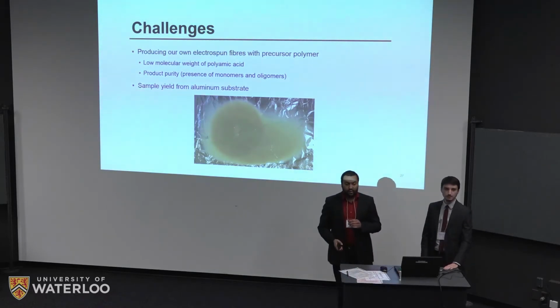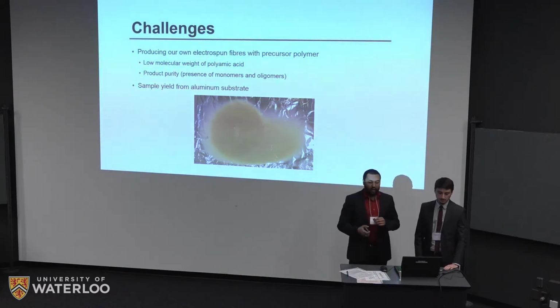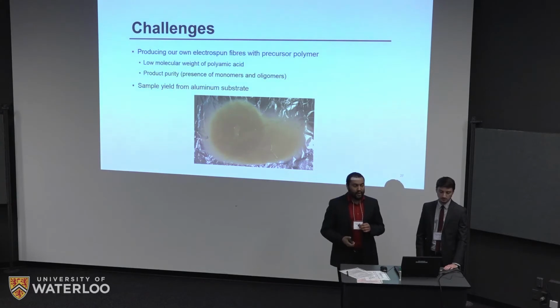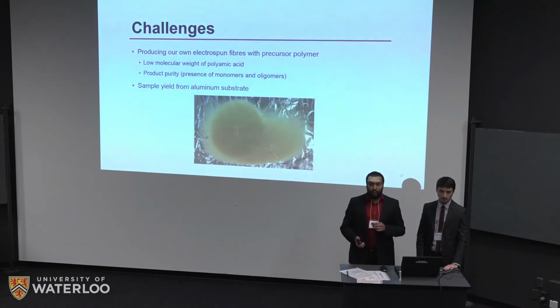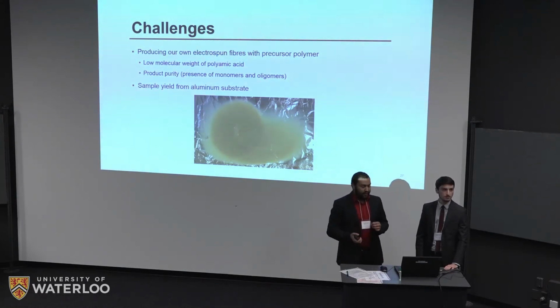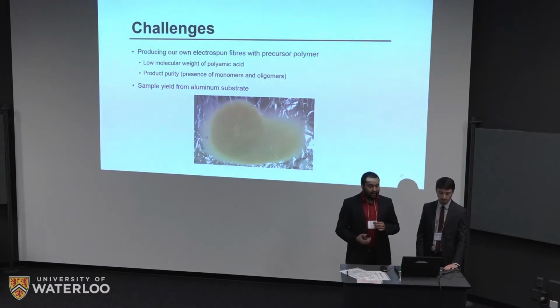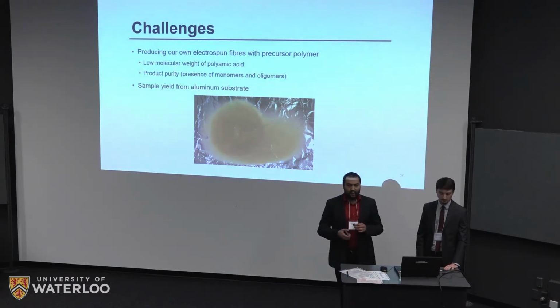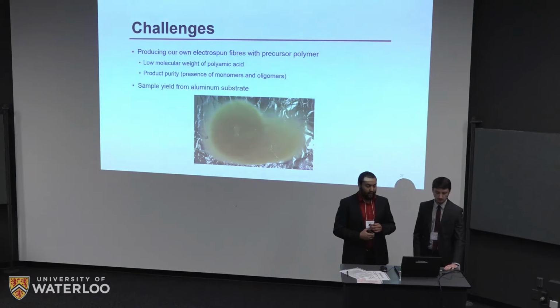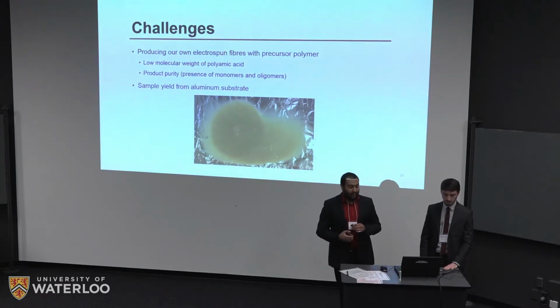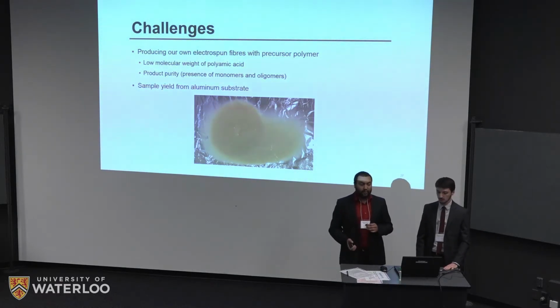So some of the main challenges that we faced when we were doing this project, probably the most significant one was actually producing the fibers using our own polymer. This ended up taking a lot longer than we anticipated. As we said, this is likely due to the low molecular weight of polyamic acid. It could also have to do with the purity of the actual sample.